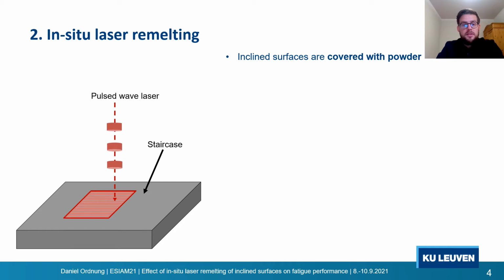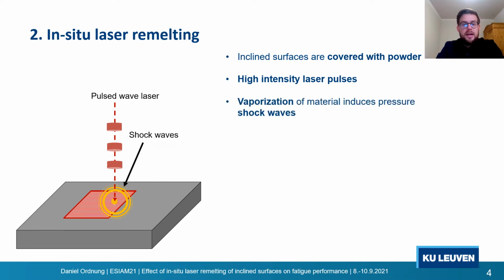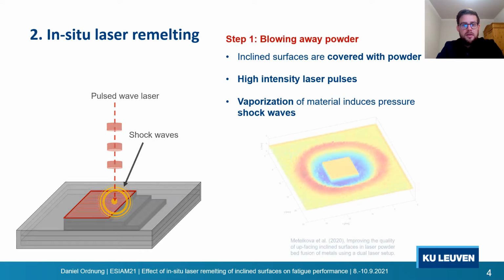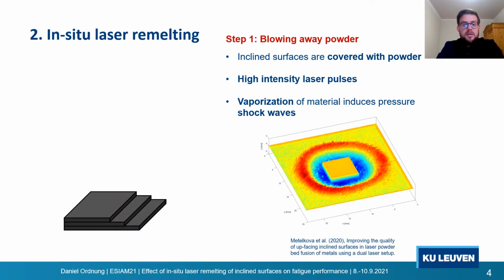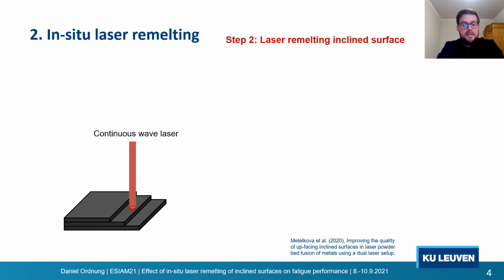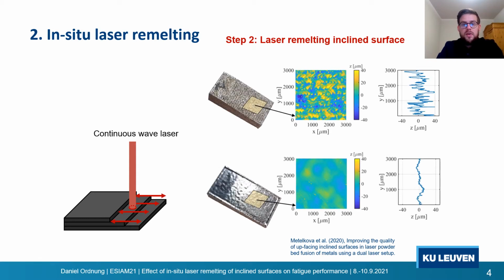We use a pulsed wave laser to scan the solid part surface. And the high-intensity laser pulses interact with the solid part surface, vaporize the material, and induce high pressure waves, also called laser-induced shock waves. These laser-induced shock waves lead to a powder bed disturbance around the part, and we use that disturbance deliberately to blow away the powder from the inclined surface. And thus, in a second step, it's possible to access the inclined surface and laser remelt it. So far, we could see that the powder removal process, followed by the laser remelting of the inclined surface, leads to a surface roughness reduction of up to 60%.